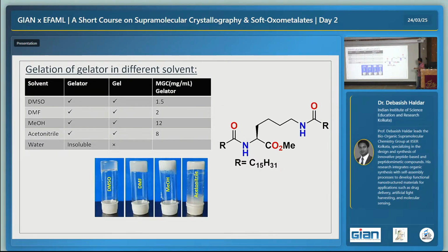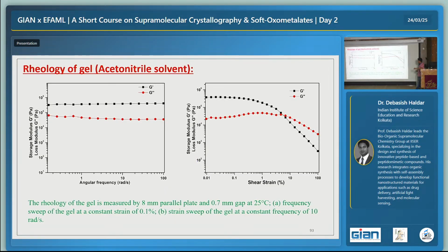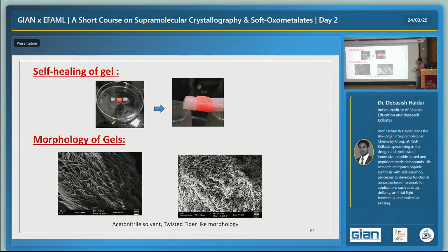Then we have made this gelator, again a different kind. Similarly, this gelator does not have any aromatic system, so it cannot absorb light. It forms gel in different solvents like DMSO, DMF, methanol, acetonitrile. We have studied the gel with rheology, so the gel is very fine. The gel is also showing self-healing nature, and this is the morphology of the gel. It's almost like Maggi noodles, very much entangled gel fibers. The confinement is very good.